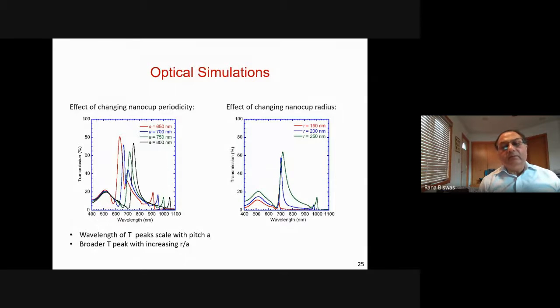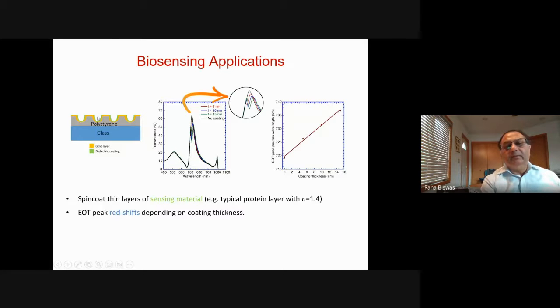Now, if you change the periodicity of the nanocups, you'll see that the wavelength of the transmission peak scales with the pitch quite readily. And if you make the radius of the cups larger, then the peak of the transmission becomes broader. And these are all well-known effects. I show the simulation results, but other authors have verified this experimentally as well. So it's good to operate in this region of a little bit narrower radius. And this has been a very good platform for biosensing.